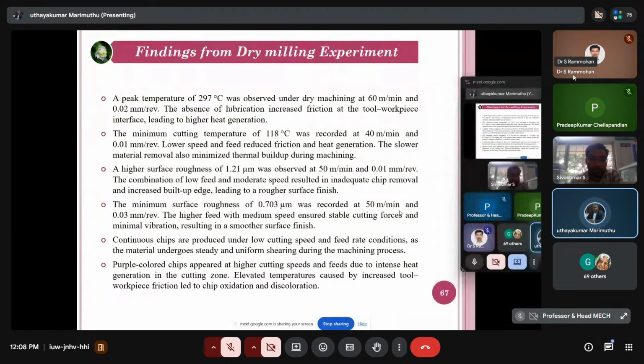I just want to summarize quickly so you should know how you have to proceed with research. That is very important. The minimum cutting temperature of 118 was recorded at 40 meter per minute and 0.01 mm per revolution. A higher surface roughness of 1.21 micron was observed at 50 meter per minute and 0.01 mm per revolution. The minimum surface roughness of 0.703 micron was recorded at 50 meter per minute and 0.03 mm per revolution.